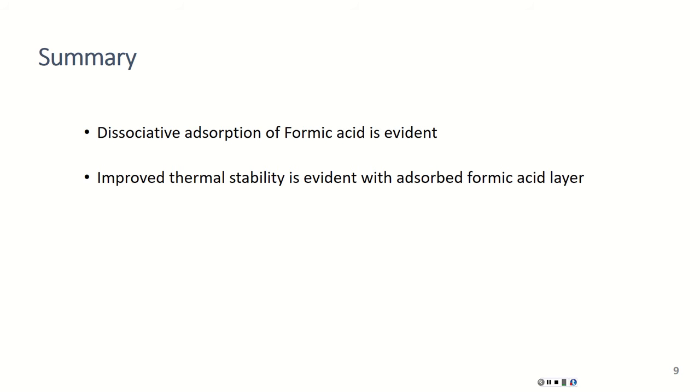Okay, yeah, very good. Well, part of the answer to your first question was in the presentation by Aaron. So if it is complete coverage of the surface by a combination of carboxylic anions and ammonium cations, or whatever, ethyl ammonium, then the frontier orbitals are not from the surface, but from the bulk, and they can participate in electronic and optical applications.